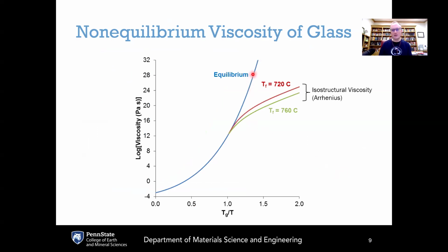So if we take this MYEGA description of the equilibrium viscosity of some liquid and supercooled liquid system, in this case for Corning Eagle XG glass, which is the glass on most televisions and computer displays, this shows the base 10 logarithm of viscosity versus Tg over T. And this region of the curve from 0 to 1 goes from infinite temperature to the glass transition temperature. If you draw a box here, this would be the Angell curve within this box from 0 to 1, going up to 10 to the 12 Pascal seconds.